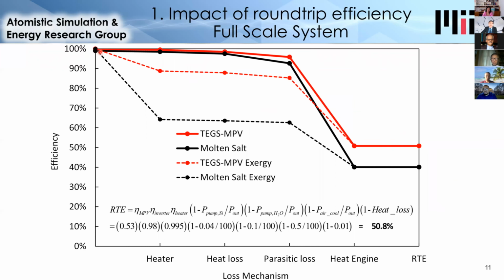You could compare this to the solid black line, which is for existing molten salt energy storage systems, like for concentrated solar power. Now these operate at lower temperatures. So during the first few parts of the cycle, they're very similar, but at the end, the efficiency of the heat engine is lower, in large part because the temperature is lower. Now the dotted lines represent another type of quantity, which is called exergy, or availability, which can be thought of as the usefulness of the energy. And the reason this is interesting to show is because of the difference between TEGs and existing storage technologies at lower temperature. So if we just look at this first interaction with the heater, in the TEG system, when we convert from electricity to heat, we only lose 10% of the usefulness of the electricity, and this is because the temperature is so high. This is why the possible efficiency of this storage system could be up to 90% if we had an ideal heat engine.